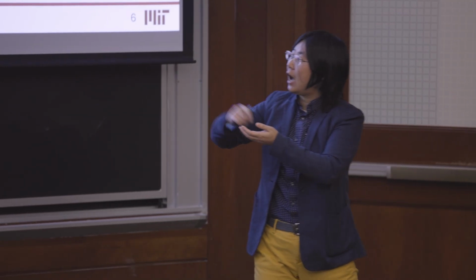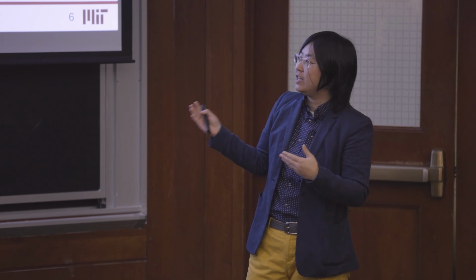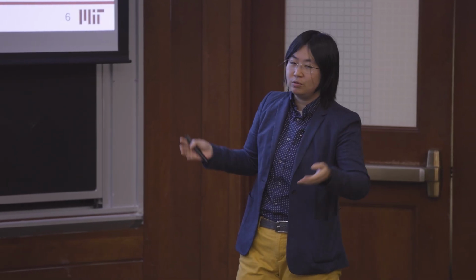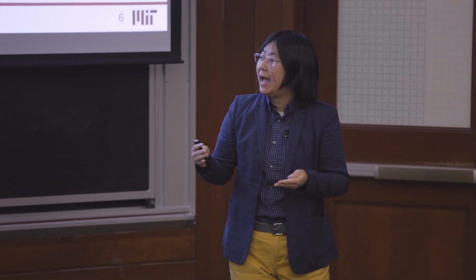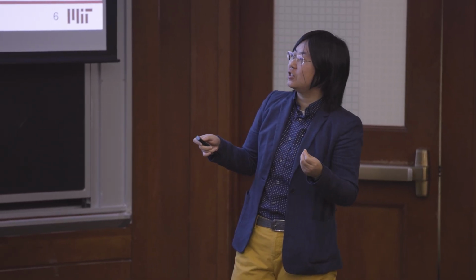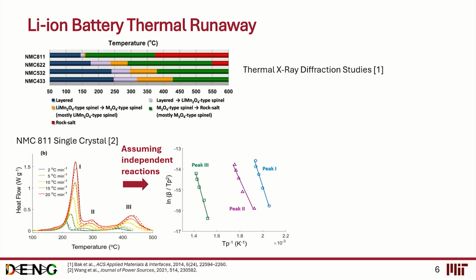For combustion scientists, we can also conduct experiments by scratching out these cathode materials from batteries and doing experiments in the so-called differential scanning calorimetry. Basically, it's a device where you put the materials in and use carrier gas to heat them up at a certain heating rate. If we have thermal decompositions that release heat, you will see peaks in the heat flow. Generally speaking, we can assume that each peak corresponds to one reaction, so we can do this experiment at different heating rates to extract the activation energy from a suite of experiments. And this is what the majority of the community has been doing.